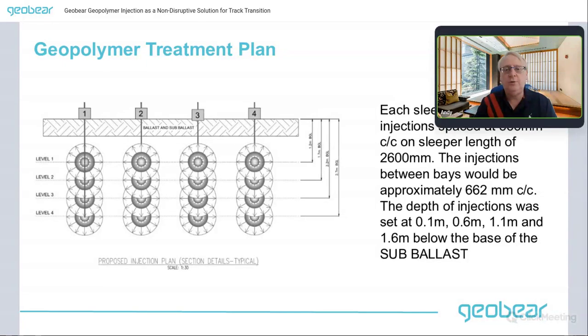So this shows you in cross section what that looks like. We have our injections going down, and we have them going across the sleeper. Each sleeper bay required 4 injections spaced at 866 millimeter centers on a sleeper length of 2,600 millimeters. The injections between the bays would be approximately 662 millimeters center to center. The depth of injections were set at 0.1, 0.6, 1.1 and 1.6 meters below the sub-ballast. So that's the depth of treatment, roughly 1.5 meters in the top of the subgrade.